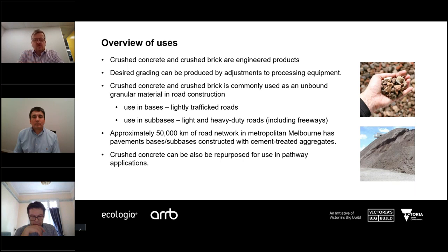re-cementing with time and causing reflection cracking, which tends to be a concern more in heavily trafficked roads, and therefore in the heavy traffic roads, the predominant use of crushed concrete is usually in sub-base material, including freeways. And there are heavy-duty motorways, freeways, arterial roads in Melbourne that have crushed concrete sub-bases. And by crushed concrete sub-base, I mean 100% of the sub-base is crushed concrete. Approximately 50,000 kilometres of the road network in Metro Melbourne has pavements that have bases or sub-bases that are constructed with cement-treated aggregates. And as you'll see later, those sub-bases in the heavy-duty roads tend to be re-cemented deliberately as part of the design concept. And crushed concrete can also be repurposed for use in pathways.